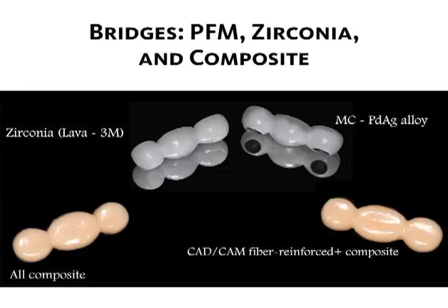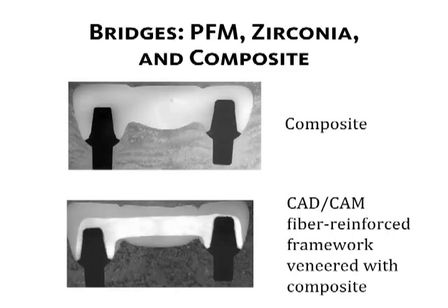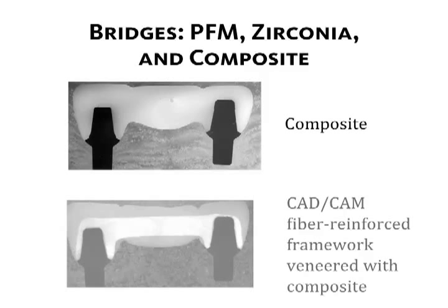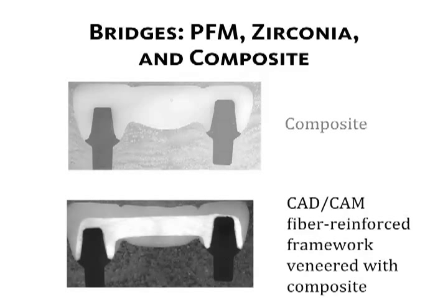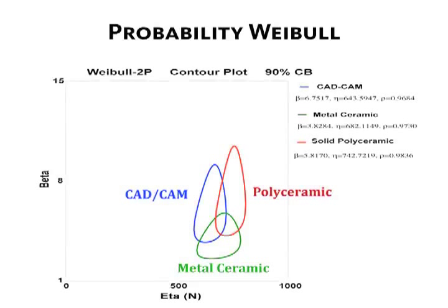When it comes to more complex geometries, such as fixed prostheses, we propose to compare metal ceramic to zirconia, in addition to composites used either as a full contour material or as a veneer onto a CAD-CAM produced fiber reinforced framework. This is how the composite groups looked in a cross-section. A full contour block of indirect composite in one group, and the other was the same composite supported by a fiber reinforced CAD-CAM framework. The results showed that composites with or even without the support of a fiber reinforced composite framework presented the same characteristic strength under fatigue as a metal ceramic bridge.